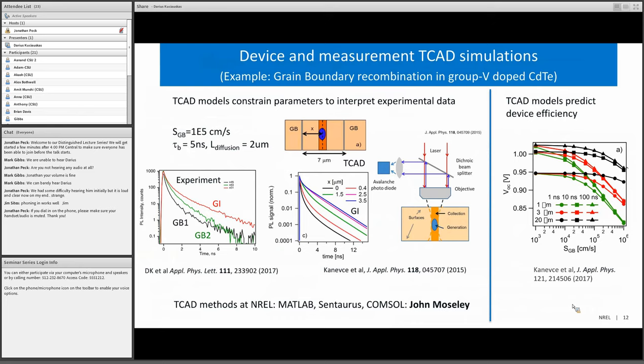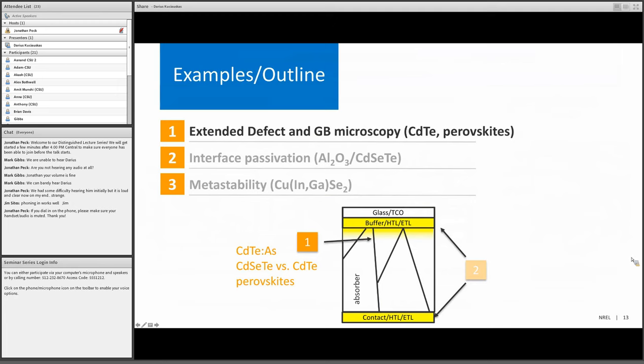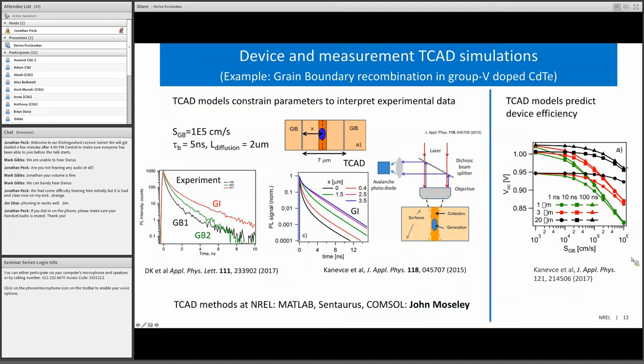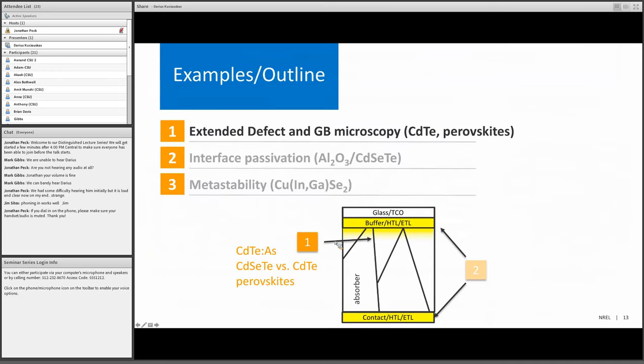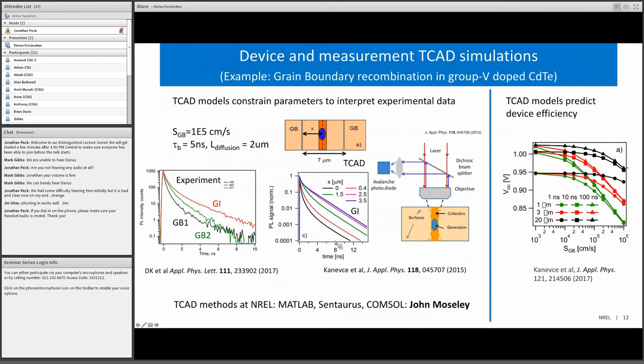Now, in addition to the experiments, we also use modeling, and the modeling is important in two ways. First, if we know the grain boundary recombination velocity, then we can calculate what is the impact on the voltage, depending on the bulk lifetime or the grain size in this material. That's a very important prediction that shows how important or less important that parameter is. The second area where we use modeling is modeling actual experiments, like in this case, the two photon microscopy data measured for cadmium telluride solar cells. Because the material itself is complex, the measurement results depend on many variables, and the modeling allows us to determine these characteristics, such as the bulk lifetime or the grain boundary recombination velocity.